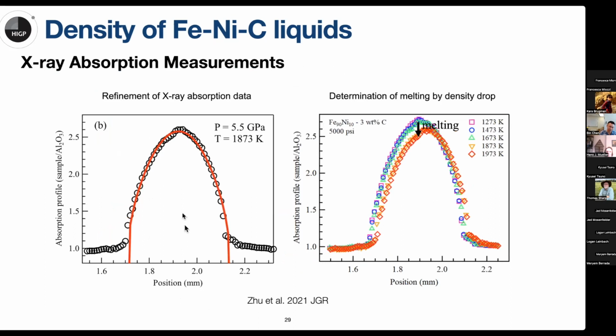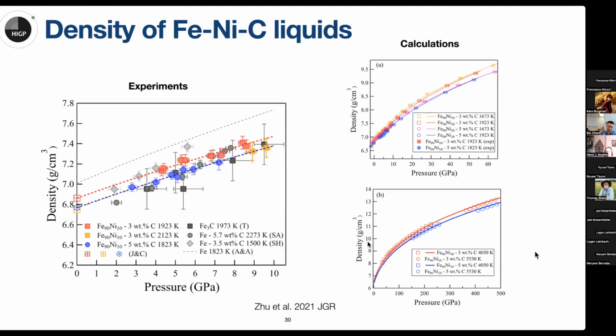And this is the representative refinement of our X-ray absorption data at 5.5 GPa and 1873 Kelvin. From this data, we can see that due to melting, there is a decrease in the density of the melt. So we performed the experiment for those two compositions, iron nickel carbon liquid, and then we fitted the equation of state to our data.